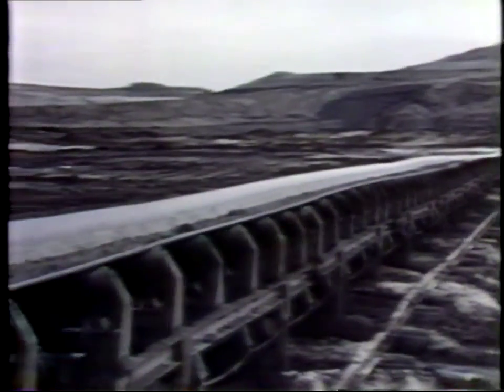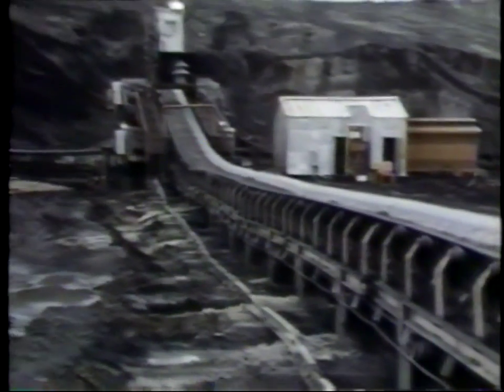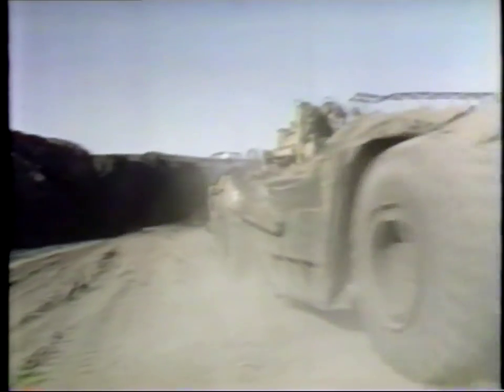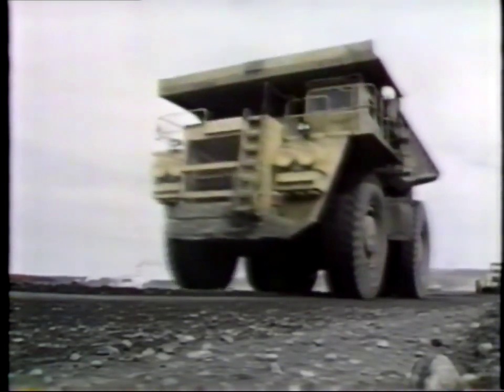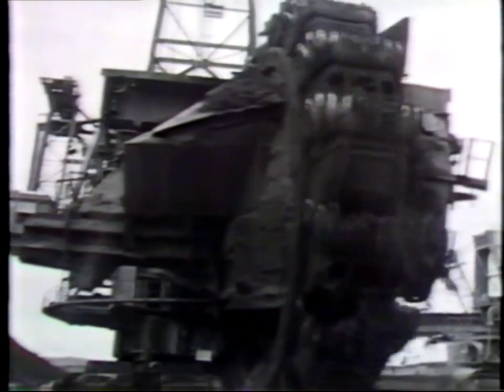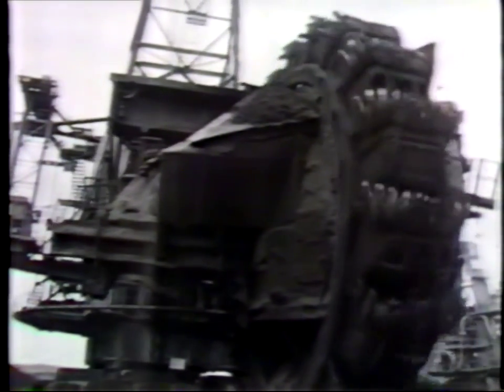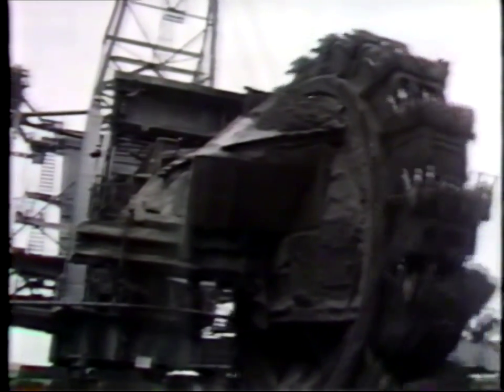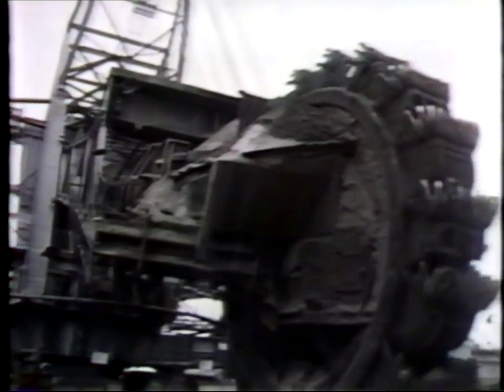It takes about 2 tons of sand to yield 1 barrel of bitumen. The conveyors have a speed of about 12 miles per hour, and the main belt is 6 feet wide and almost a mile long. Keeping the machinery in operation is something of a problem. In the heat of summer, at perhaps 85 degrees Fahrenheit, the sticky tar sand gums things up, and in the winter it freezes as hard as rock. When the excavation was first attempted in the winter, the teeth of the buckets glowed red and tore off within 4 hours.